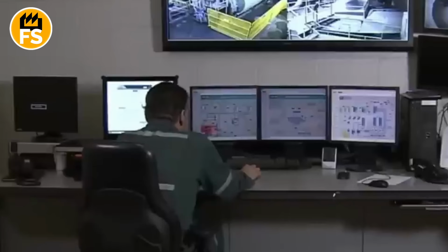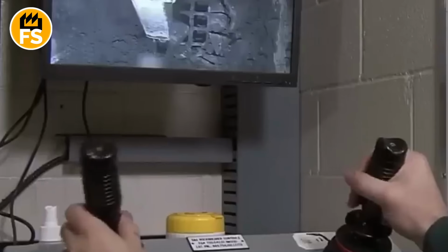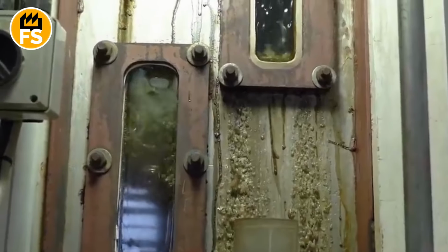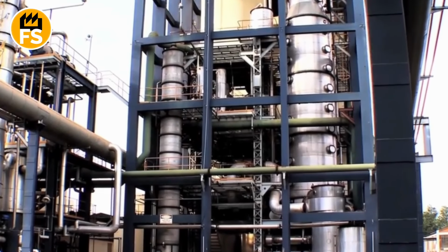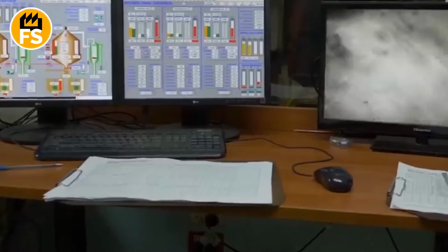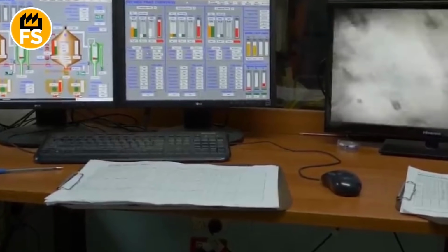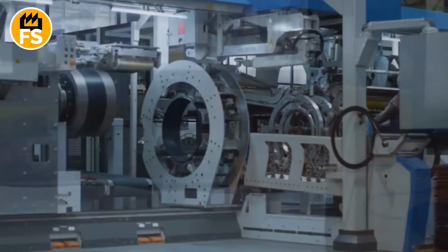To make the reactor work, we need to increase the concentration of this energetic uranium-235 from 0.7% to 3 or 5%. To begin enrichment, the solid uranium must be converted into a gas. It is treated with hydrofluoric acid, turning it into uranium tetrafluoride, and then with fluorine to obtain uranium hexafluoride. This is a very corrosive and dangerous compound, which has a unique property. It becomes a gas at a temperature slightly above room temperature, and so this gas, packed in special containers, is sent to an enrichment plant.